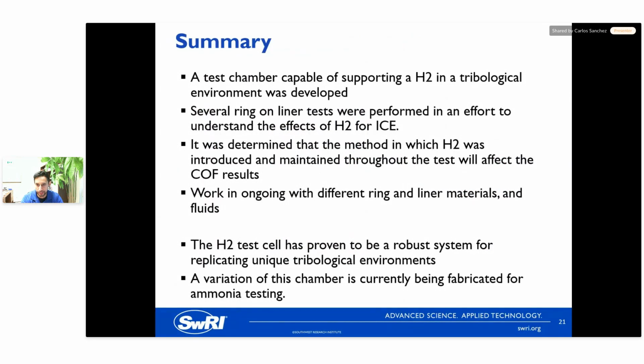We ran several ring and liner tests for hydrogen for an ICE environment, and we determined that the method in which you introduce hydrogen into your system really affects the results. So if you're really trying to force hydrogen in there, then you'll see results. But in a typical case, hydrogen tends to dissipate really quickly. So even if you have your parts sitting in an autoclave, under pressure and hydrogen for a few days, you take them out of there, you're not going to see too much of a difference. You really need to pump the hydrogen in.